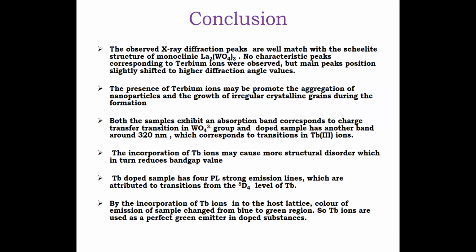Then here is the conclusion of my study. About the structural studies, the XRD patterns revealed that all structural peaks are well matched with the scheelite type of monoclinic lanthanum tungstate. Due to terbium inclusion, the main peak position slightly shifted to higher diffraction angle values. Both the samples exhibited irregular size and shape. The presence of terbium ions promotes particle aggregation and growth of more irregular crystalline grains, which is evident from some images. EDAX spectra confirm the elemental composition and purity of the sample.